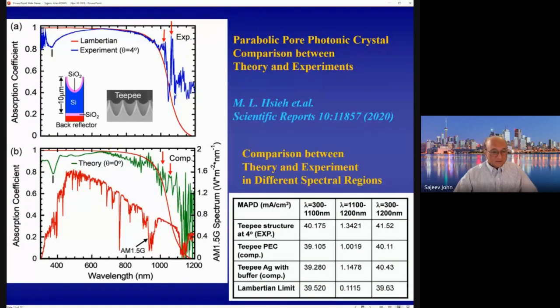So there's some slight differences between the theory and the experiment. But here's a table summarizing the results of what is observed experimentally in the different wavelength regions, 300 to 1100, as well as 1100 to 1200, and the total. So the experimentally observed photocurrent density turned out to be 41.52, which is well above the Lambertian limit, which for this structure would be 39.63 milliamps per square centimeter.